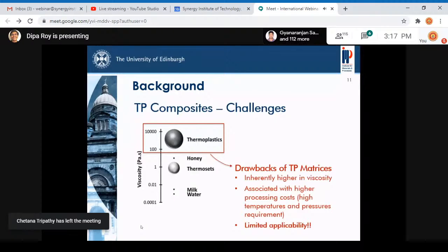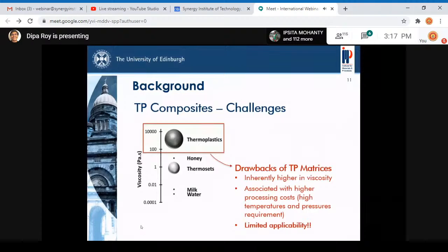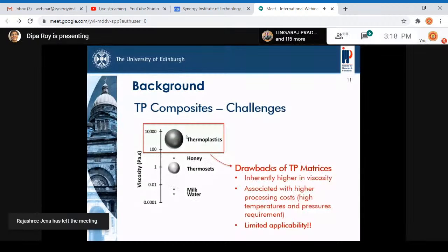But there are some challenges associated with thermoplastic composites. We know thermoplastics are available in the form of powder, pellet or granule, but they all have high molecular weight. Because of this high molecular weight, they have a very high viscosity. That's why it is not easy to manufacture thermoplastic composites with fibers. We have to use high heat and pressure to wet the fibers, or to impregnate the reinforcement materials with this matrix. On a scale of viscosity, you can see thermoplastics are placed very high up. They are much higher in viscosity than conventional thermosetting resins, which are much more liquid.